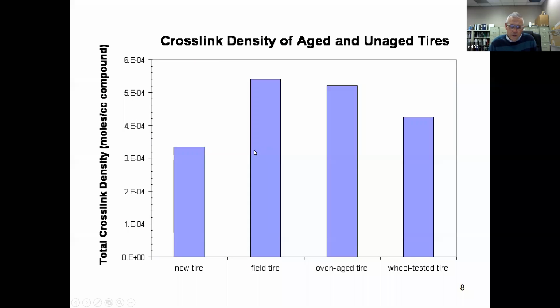So the first test, we had dissected the rubber between the steel belts, and we measured crosslink density by swelling. So this is swelling in toluene and then subsequent calculation of the crosslink density using the Flory-Rehner equation. So here's the crosslink density of the new tire, and you can see in each of the aged tires, the crosslink density is higher, artificially aged by running on the road wheel.